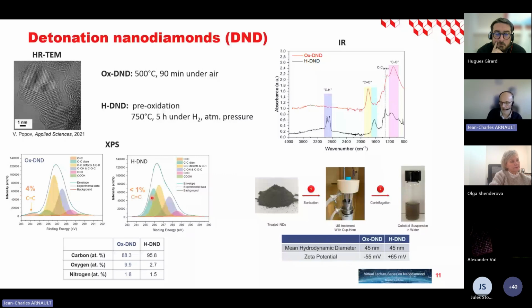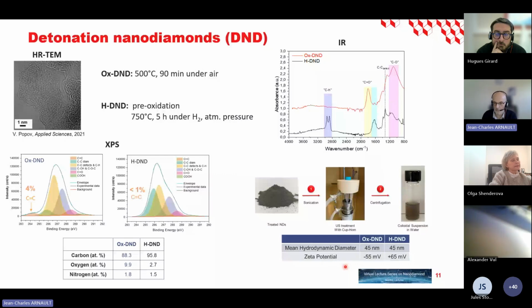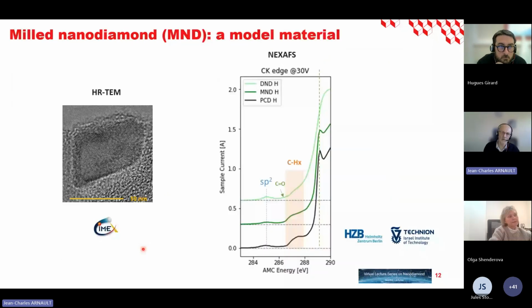Both surface chemistries can be suspended in water, this is well known, and you get the expected zeta potential, the negative one for the oxidized particles and the positive for the hydrogenated one. Looking at the milled nanodiamonds, something very particular is observed. This is the very good crystalline quality of these particles. You can see here a high-resolution TEM picture of such a particle.